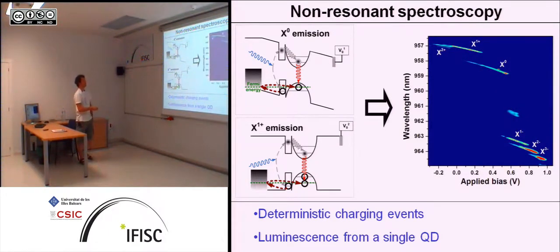And if you look at the spectroscopy now, this is luminescence spectroscopy, so we use the microscope system to collect the emission of the quantum dot, we use some filters to block out the excitation laser, and then we change the gate bias. So we now look for this one here, this state is X0 emission, this would be here, and now all we have to do is tune the gate bias to a different voltage, and then you jump to this other quantum state where you have the second level of the valence band in resonance with the Fermi energy, and then you get an additional carrier, and that's the next quantum state inside the quantum dot.